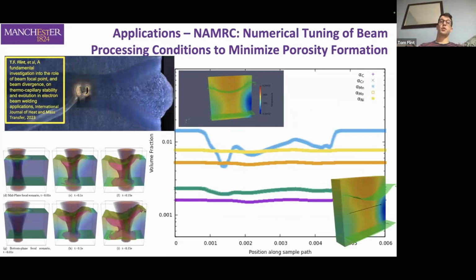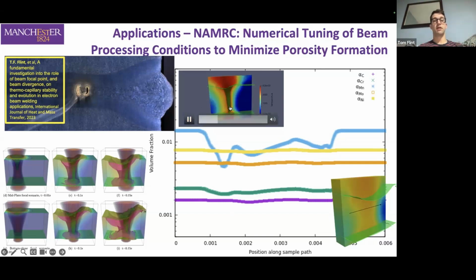This is from some work that we did with the Nuclear Advanced Manufacturing Research Centre. They are basically trying to get power beam welding into the nuclear codes and standards. The problem is that although you get these really high penetrations and really high productivity with these joining processes, when you turn off that beam, as maybe was shown in that video, so we've got the keyhole generated, it's moving along a seam of a joint, then we turn the power off, the keyhole collapses.